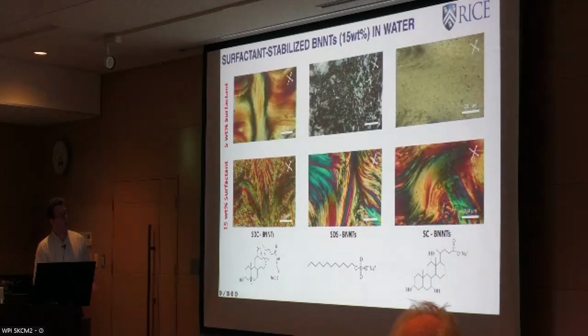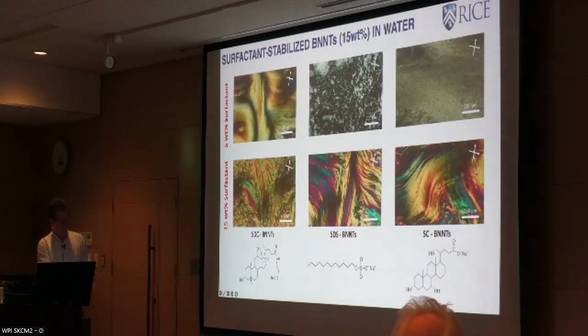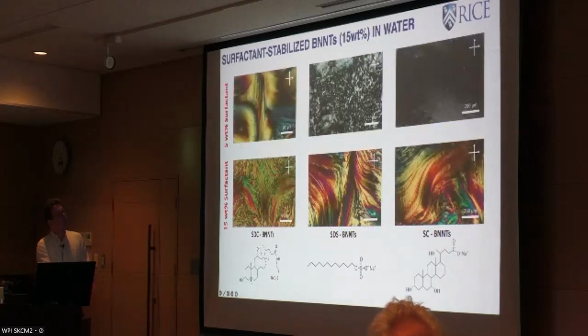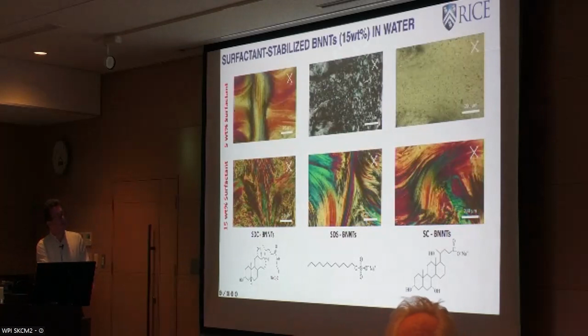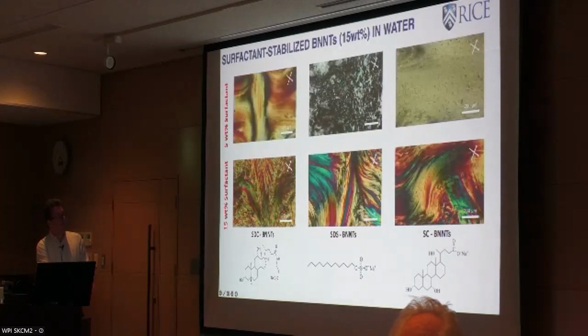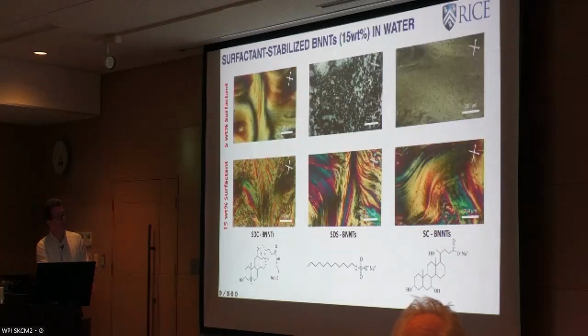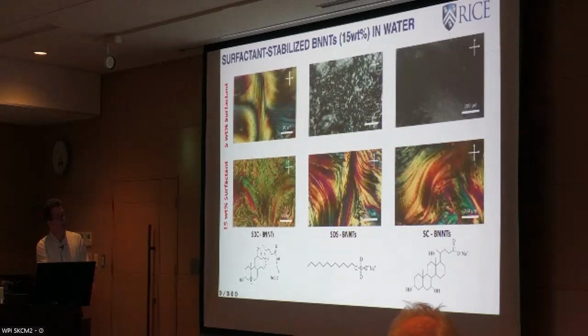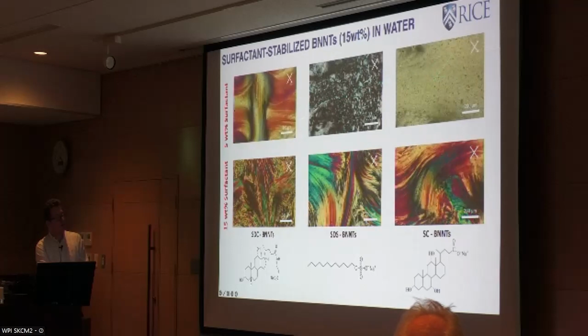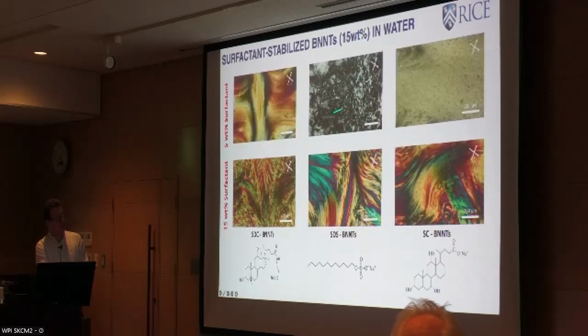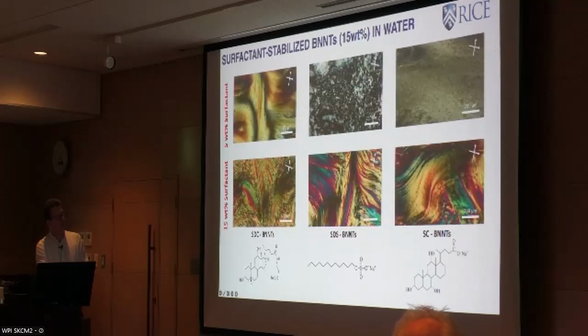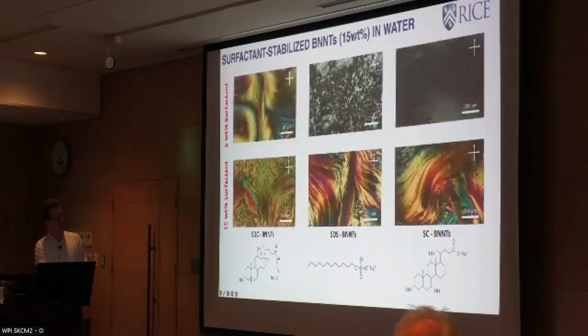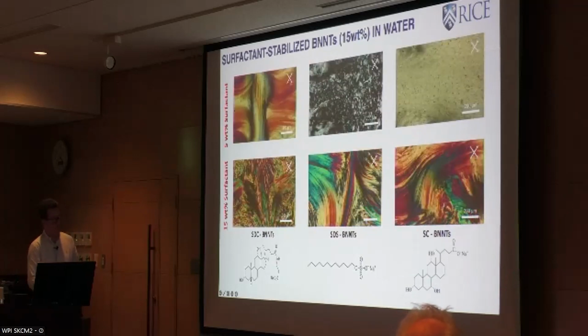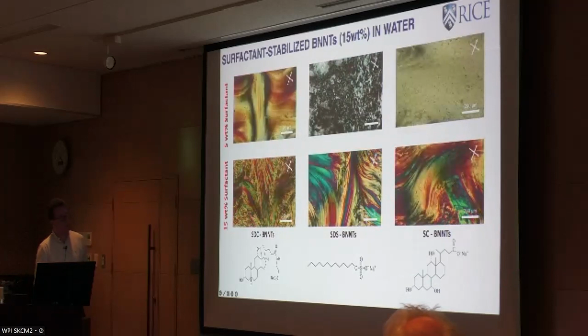We can also do this in surfactants. Now, this is again purified boron nitride nanotubes at 15%. This is with 5% surfactant. This is 15% surfactant. What you see is that at the lower concentration of surfactant, the type of surfactant you use seems to be very critical. At higher concentration of surfactant, the behavior seems to be a little bit more similar.